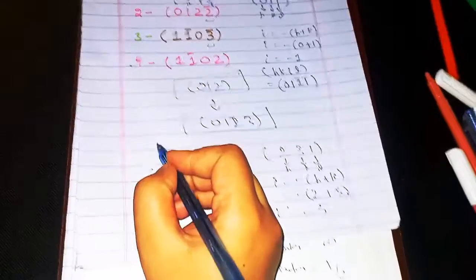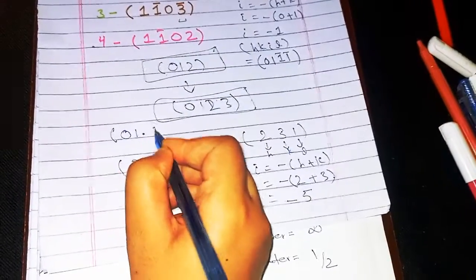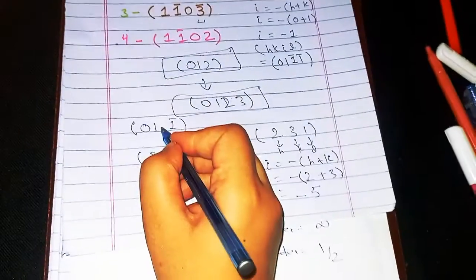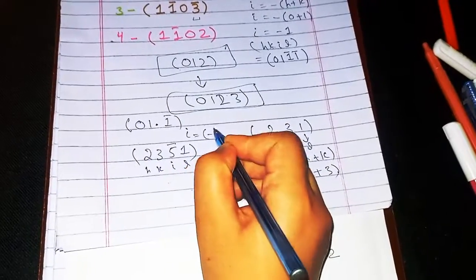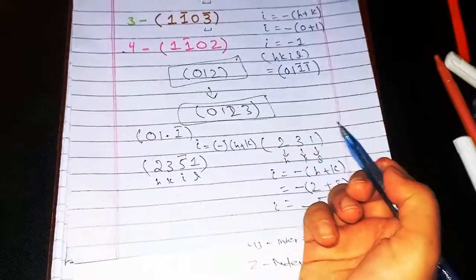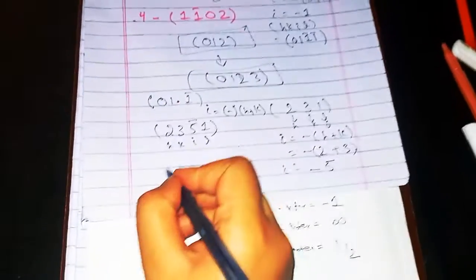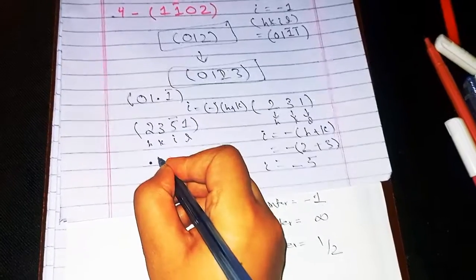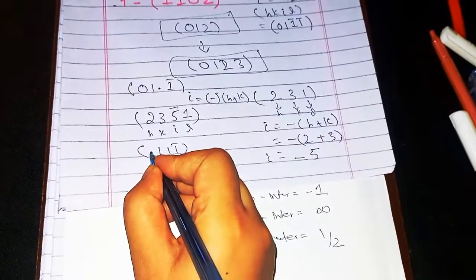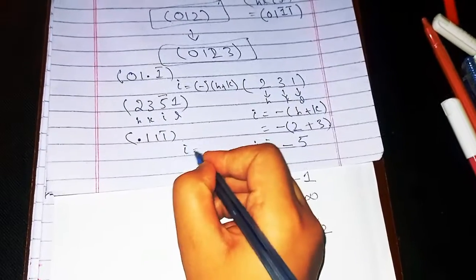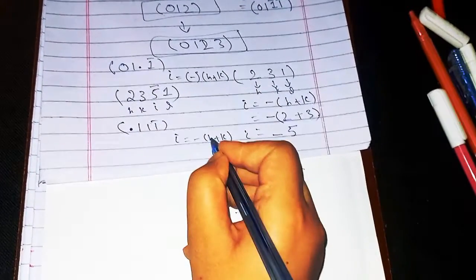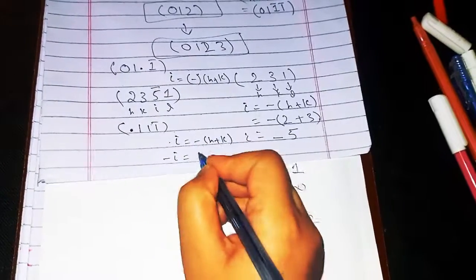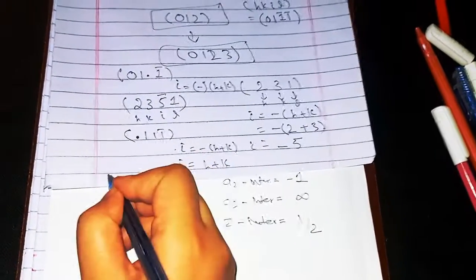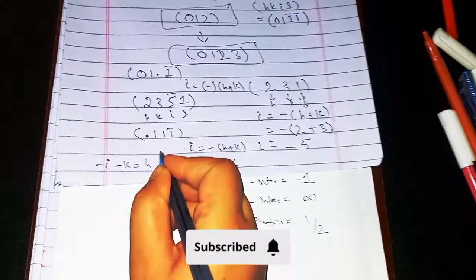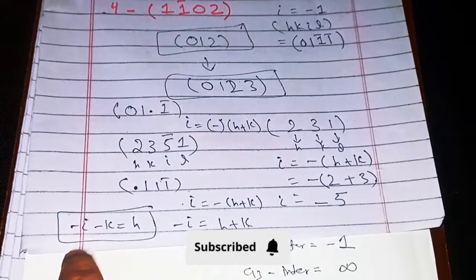And in some other instances, they write it like that: 0, 1, dot, 1 bar, and the dot is actually I, and you will find I using the same formula, minus of H plus K. That is really simple. Sometimes they shift the dot, for example, to the first place. You know that it's the place for H. You can find H from this formula again. You can take the negative, so H plus K equals minus I, and taking K to this side, it's minus I minus K equals H. If you know two of them, you can find the third one. That is the beauty of Miller-Bravais indices. That is really simple.